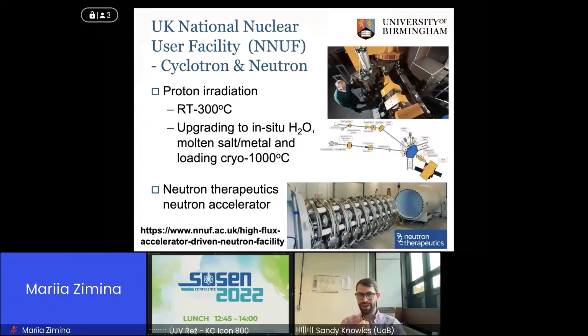Particularly, there are lots of very good irradiation facilities at CVR. In Birmingham, we're very fortunate to have our own cyclotrons, so we can do proton irradiations up to temperature, as well as we're getting upgrades for in situ corrosion and mechanical loading, including high temperature. And we've received, and I think by the end of the year it will be operational, a neutron accelerator. So I think we can still get up to 0.1, maybe a bit more DPA. So we can start to do some irradiation studies as well as neutronic studies. So this is probably one of the higher energy and damage levels for an accelerator system compared to reactor-based systems, where probably you can get some higher damage levels. But there are differences in terms of the energies involved as well.